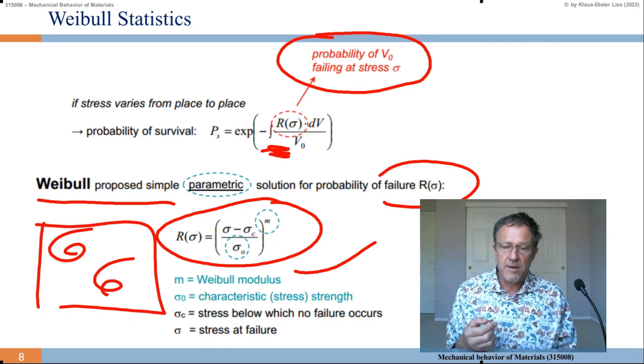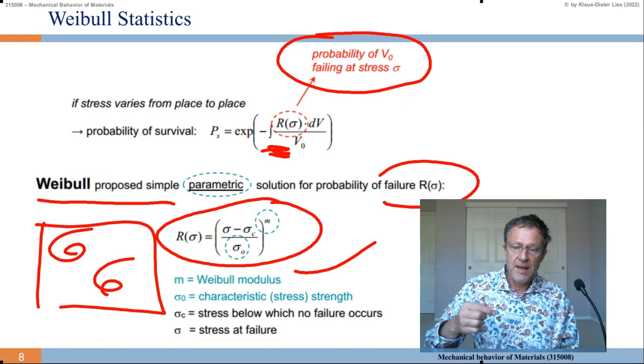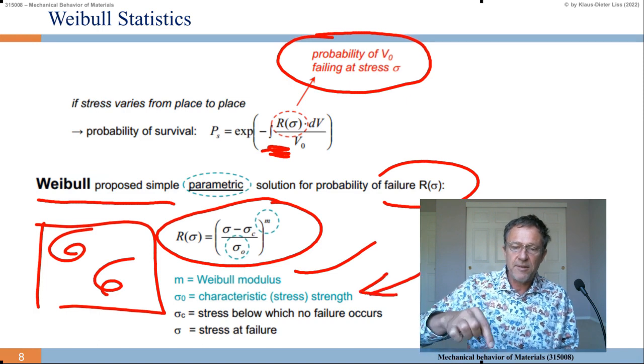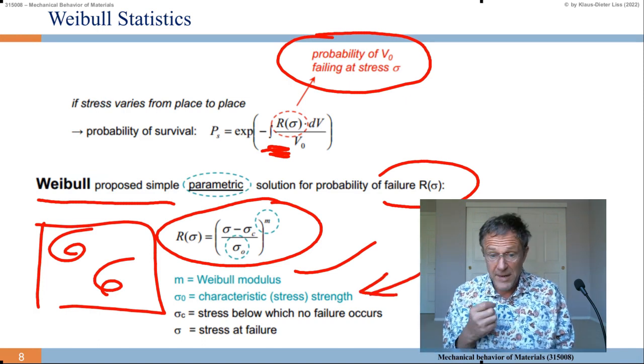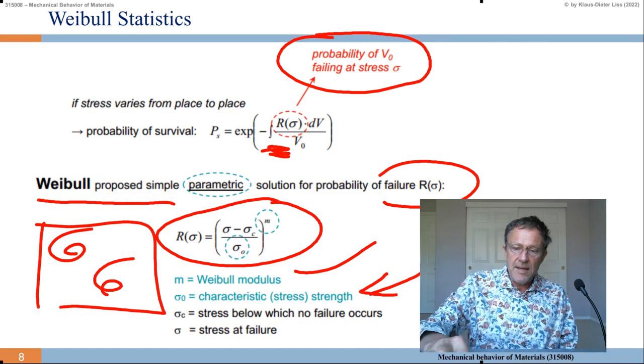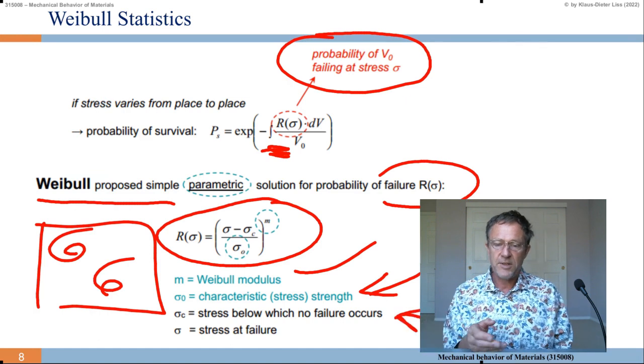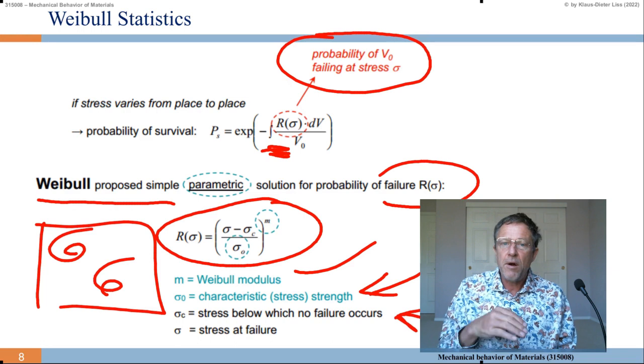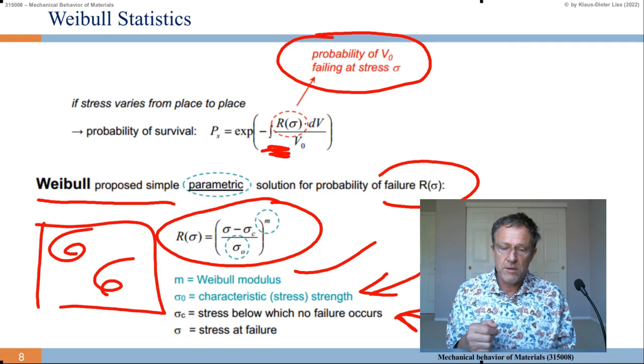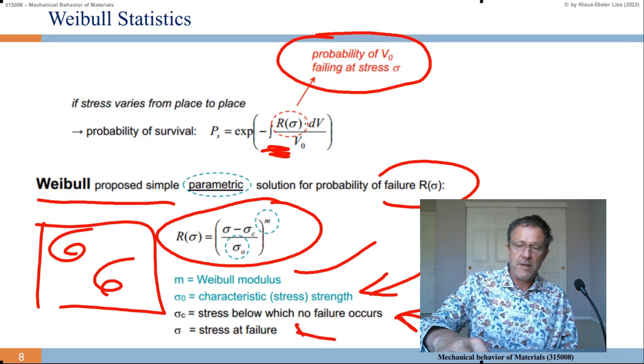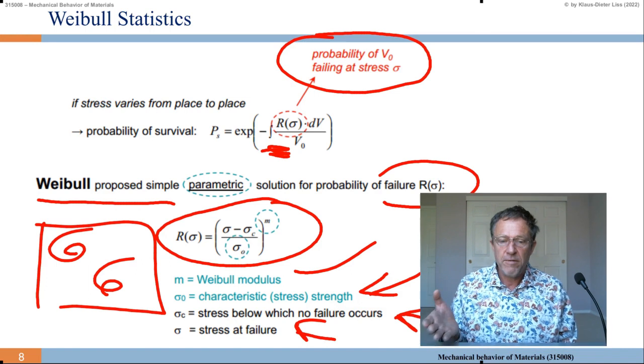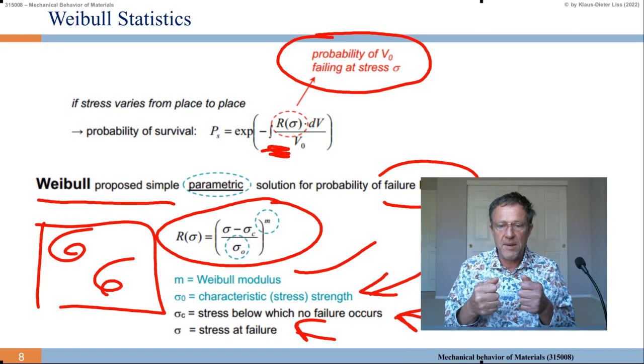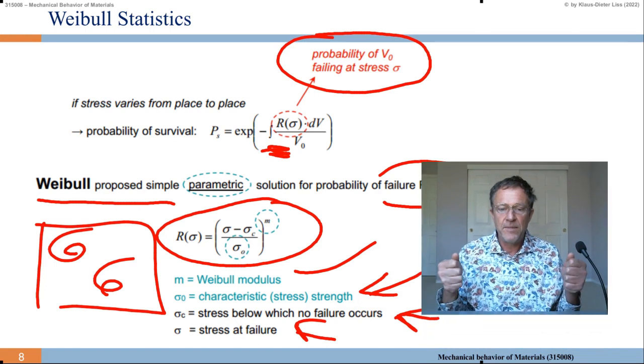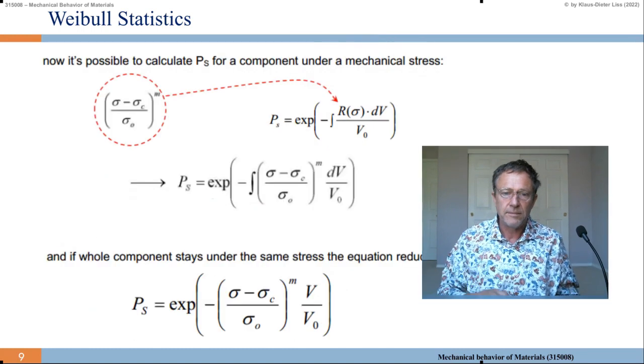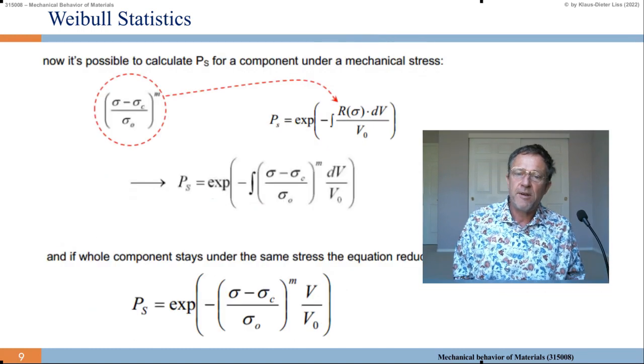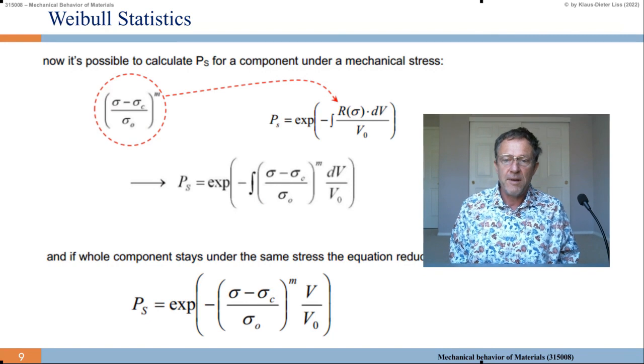And this m we call the Weibull modulus. Sigma 0 is a characteristic strength, which is in the denominator there. And sigma c is a critical stress. If we go below this critical stress, no failure occurs. And sigma is the variable, so this is the stress at failure, what stress in an experiment we apply until it fails. So now it's possible to calculate PS for a component on the mechanical stress.